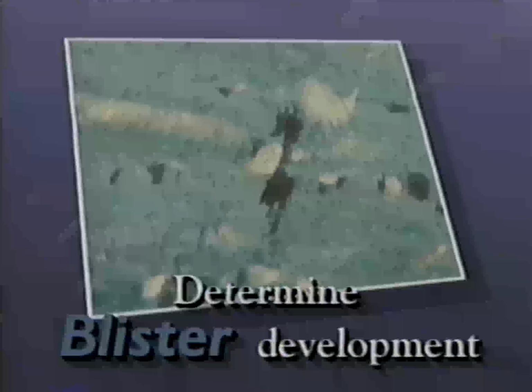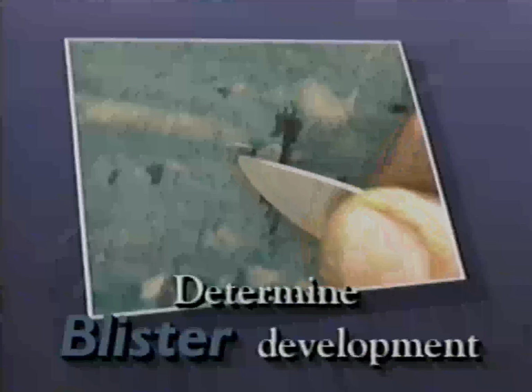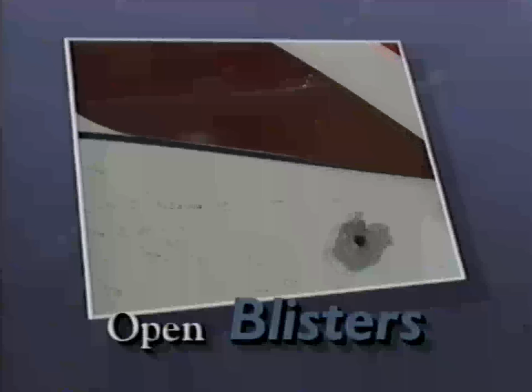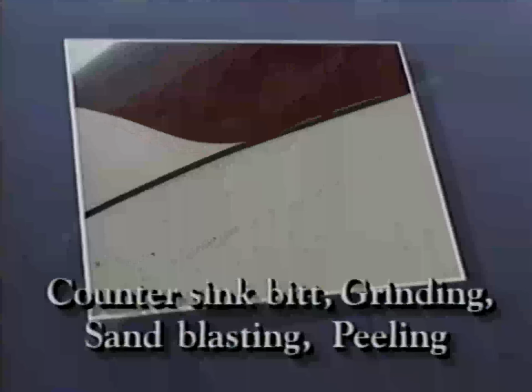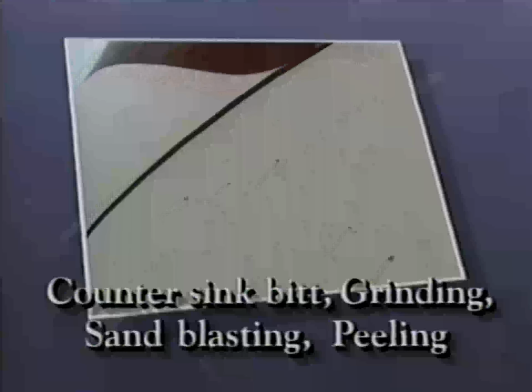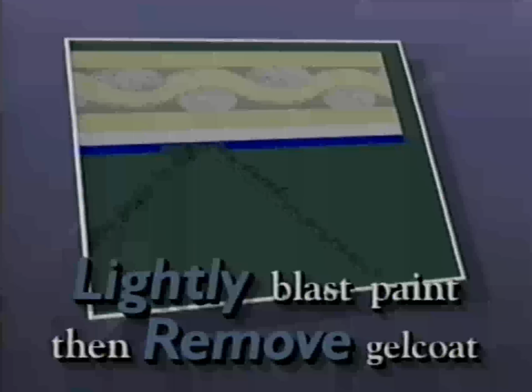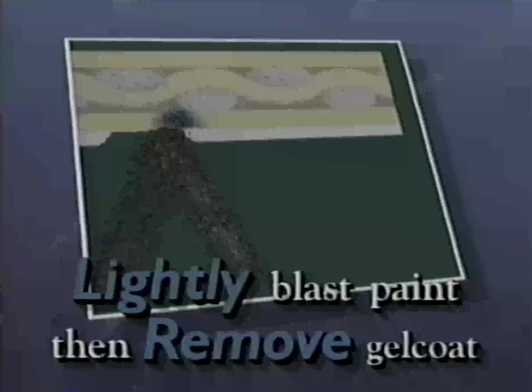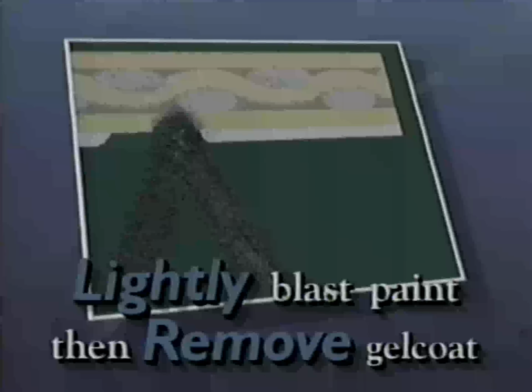Now, let's review the steps to repair Gelcoat blisters. Determine the degree of blister development. Open blisters by using one of these methods: countersink bit, grinding, sandblasting, or Gelcoat peeler. If you sandblast, use medium slag and lightly blast the anti-fouling paint off prior to attempting to remove the Gelcoat.